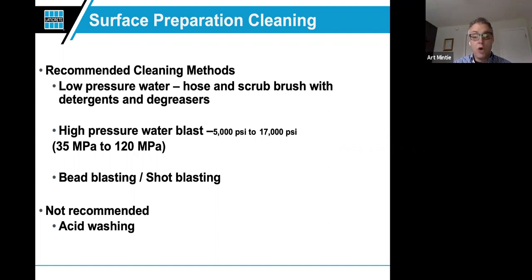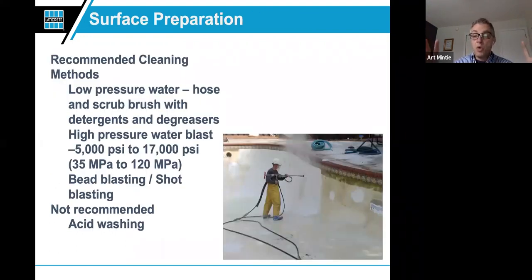But the key here is we don't want to use acidic washing methods. The acid does not like cementitious surface. That's why you're using it to clean off cement laitance and other contaminants. But guess what? The installation materials are also cement-based. And that acid is never neutralized completely, and it can have a deleterious effect on the installation materials, because as soon as it gets wet again, it will reactivate and it aggressively attacks the cementitious materials. So our experience has been: don't use acid, use high pressure or low pressure wash or some other sort of mechanical means.